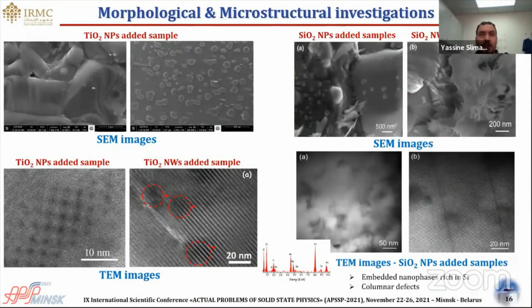The inclusion of nanoparticles in high temperature superconductors could, of course, also generate some structural defects. The TEM micrograph of YBCO sample added with titanium oxide nanowires showed, for example, the presence of inhomogeneity as well as structural defects like twins.